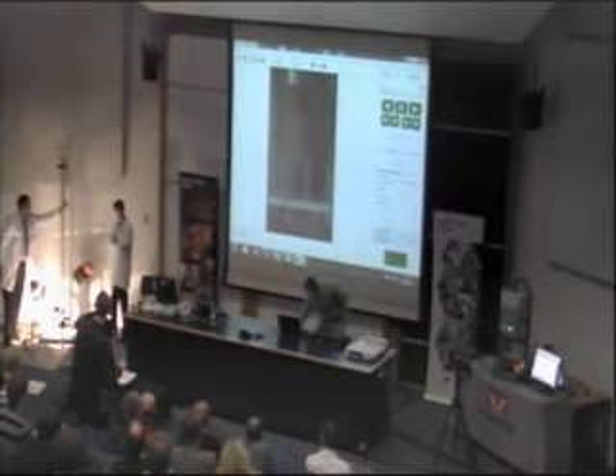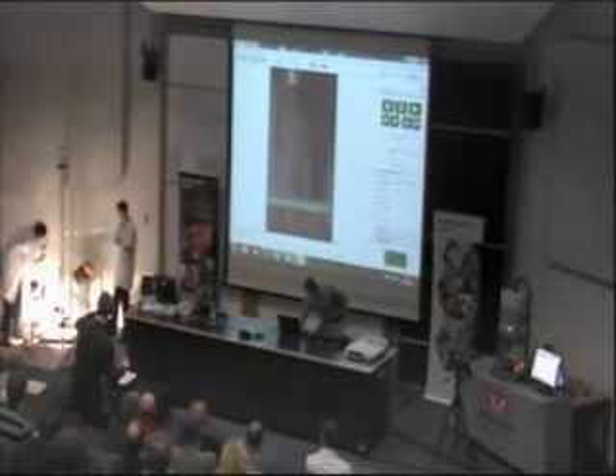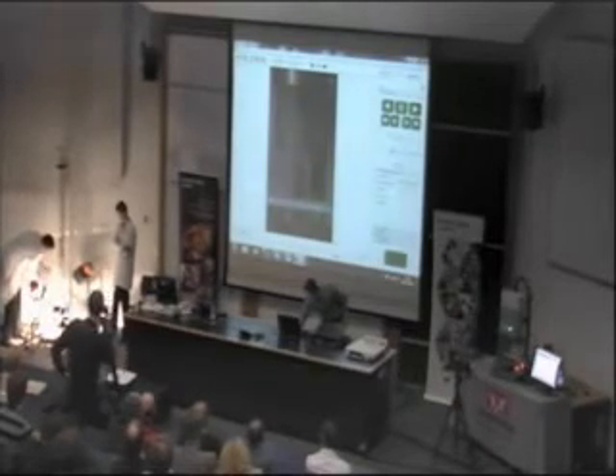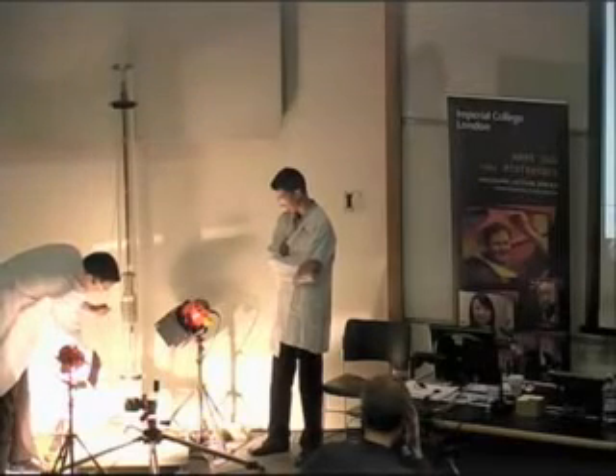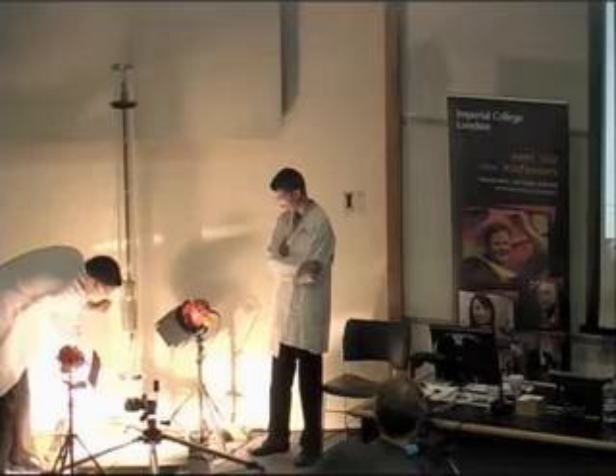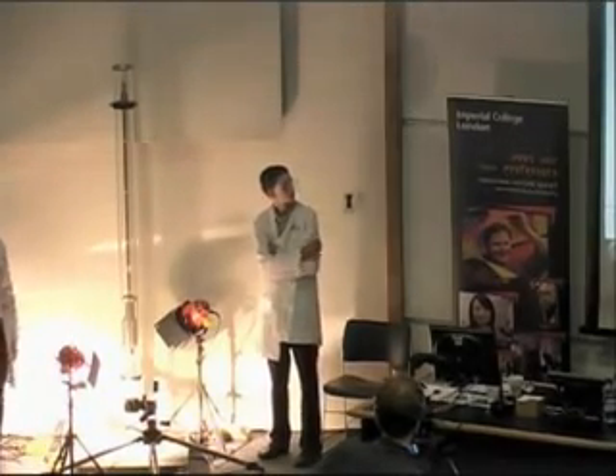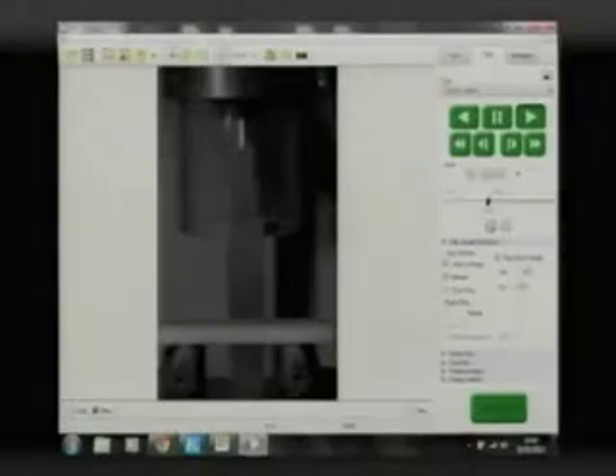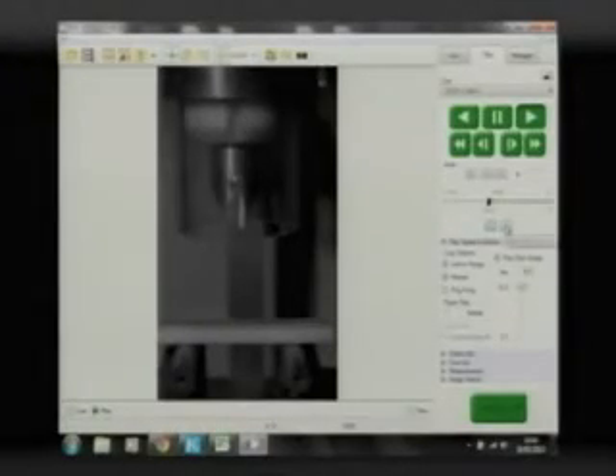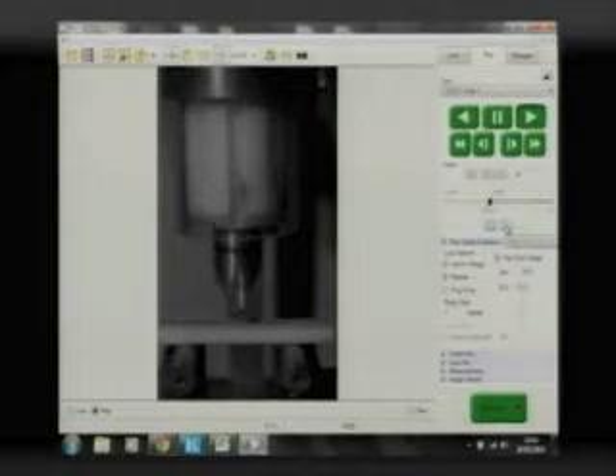So the point is that, of course, in this dynamic test, this material stiffens up and is much more prone to fail. And we've got the data captured there. So you're looking at the end of the barrel, or the end of the drop weight machine. And we're going to process the data and play this back in slow motion. In the old days, we used to do it with film, but these days it's all captured digitally.